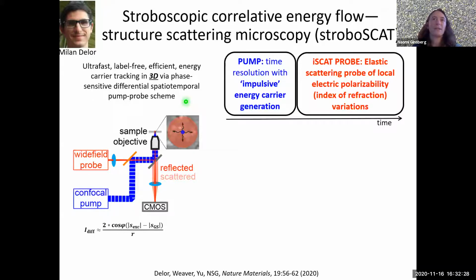And so since interferometric scattering is the probe, but we're doing a stroboscopic technique, Milan, the originator of this work in my lab, dubbed it stroboscat. And we're measuring the properties of excited state species, but we can also, just by probing, measure the ground state, and that provides an in situ structural correlation. So the key difference here is that whereas in iSCAT, we're measuring particles or structures, by first pumping the sample with a localized spot, we're measuring quasi-particles instead, like charge carriers and excitons.